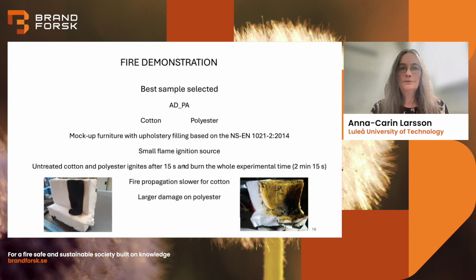We started with a small flame ignition source, and we could see that untreated cotton and polyester ignite after 15 seconds and burn the whole experimental time. This is untreated cotton, and here is untreated polyester. We can see that cotton burns a bit slower, and we get much more damage on the polyester.